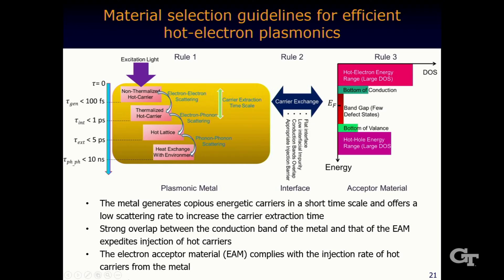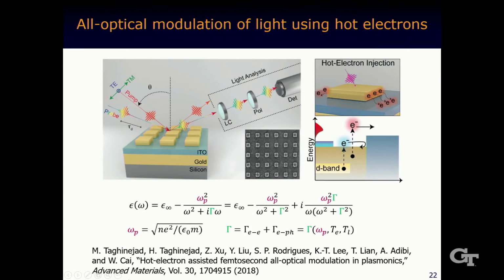So some general design principles. Basically, we need to make sure that there's a very efficient generation of hot carriers on the metal side, and the junction in between the metal and the electron absorber or acceptor should be appropriate so that a good amount of electrons can escape, because the transfer probability is related to the junction height, which is related to the relative magnitude of electron affinity in the metal and that of the semiconductor. And in the acceptor material, we need to make sure that sufficient electron density of states is allowed along with the right energy lineup.